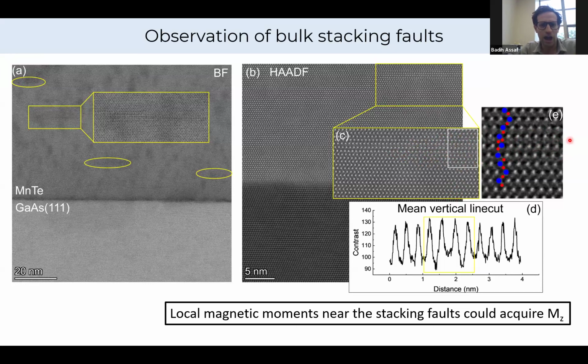It's also not known how the local moment is affected by these stacking faults, if this creates an unexpected canting or some Mz components that are not expected in the pristine structure. So we want to understand the anomalous Hall effect in the presence of these stacking faults and this thermal strain.